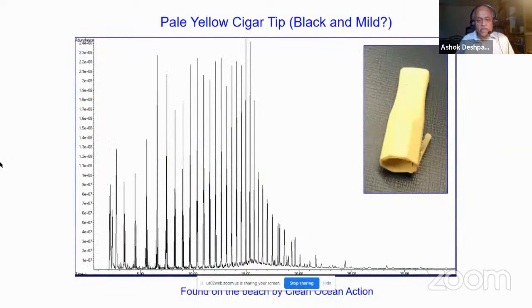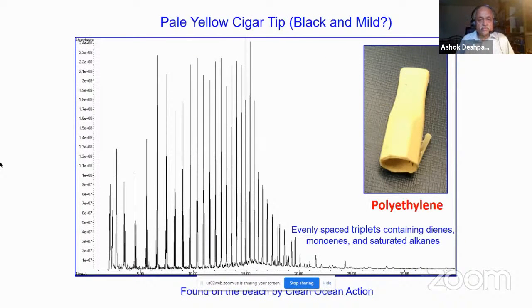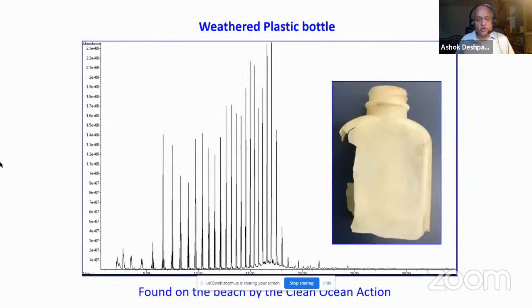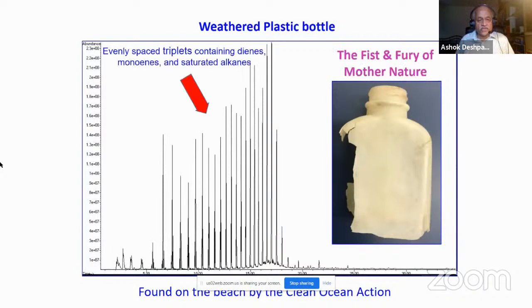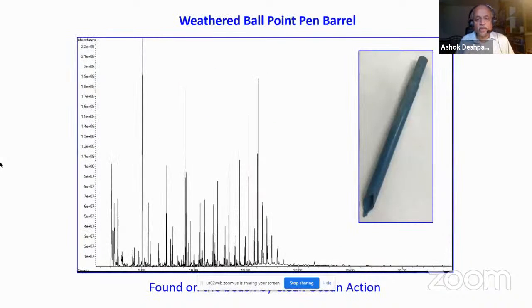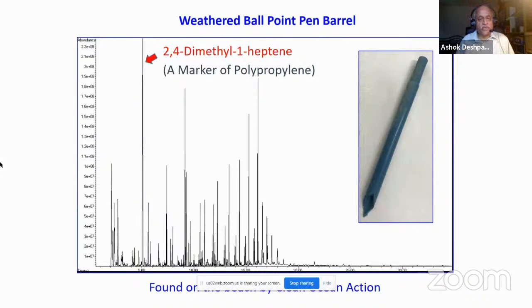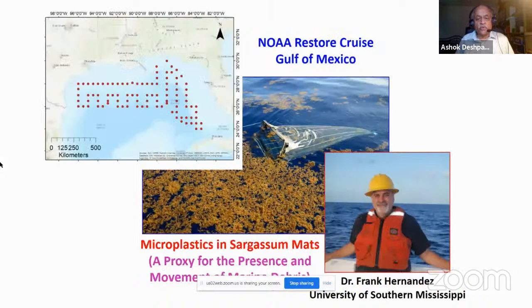This plastic tip contains a signature of polyethylene. This weathered plastic bottle also has a signature of polyethylene. We were very surprised to see that the fist of fury of Mother Nature banged it up so much, but it did not make any difference in our data quality by using pyrolysis GCMS. This ballpoint pen contained the signature of polypropylene. So we went to work with Dr. Frank Hernandez of University of Southern Mississippi. He collected samples for us from sargassum mats in the Gulf of Mexico.